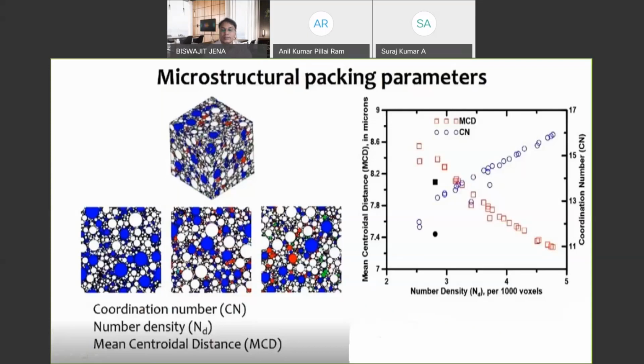It also tells me indirectly that if I have more particles around one cement grain, it is more likely to react because there are reacting species around the particle. It does not tell me exactly what, but it gives me a broader range. Then number density. The number density will tell me how many particles are there in a unit volume. The more particles, the denser the structure. If the particles are smaller, you will have more particles and a denser structure. Then the third one is the mean centroidal distance. If I take one cement particle, I will know the mean centroidal distance between that particle and like or unlike particles. It could be cement, fly ash, or limestone.